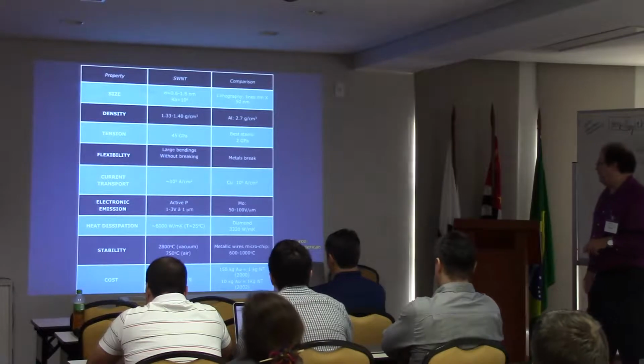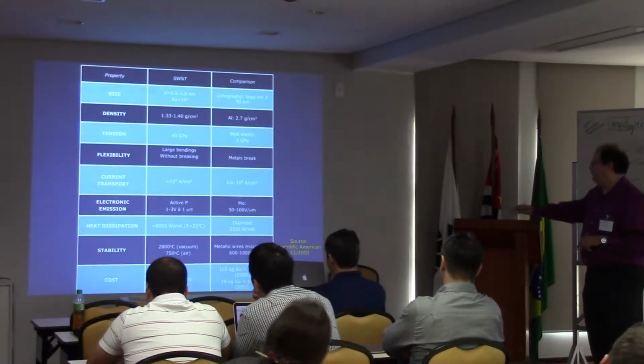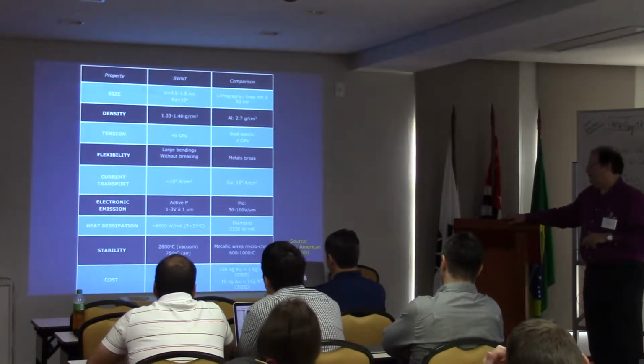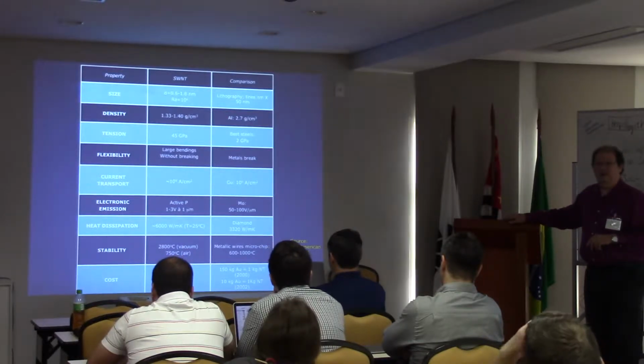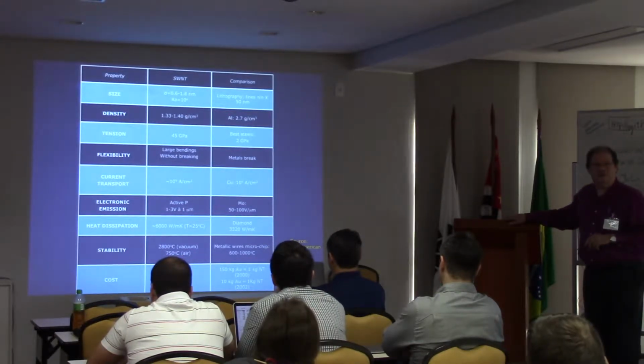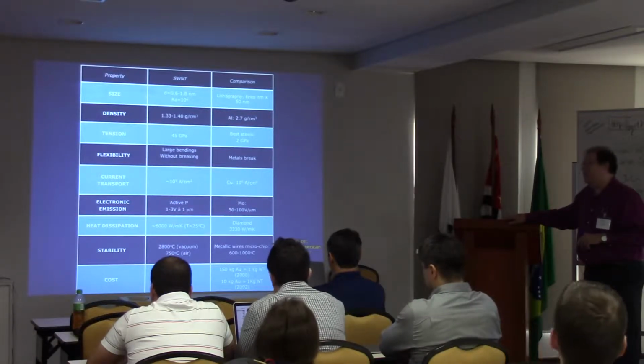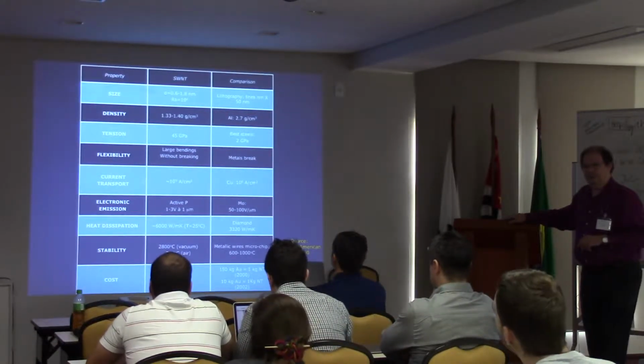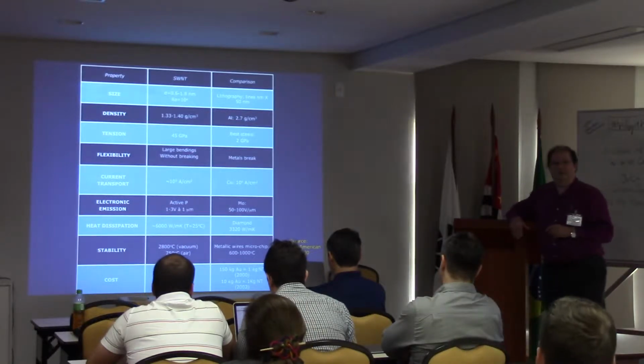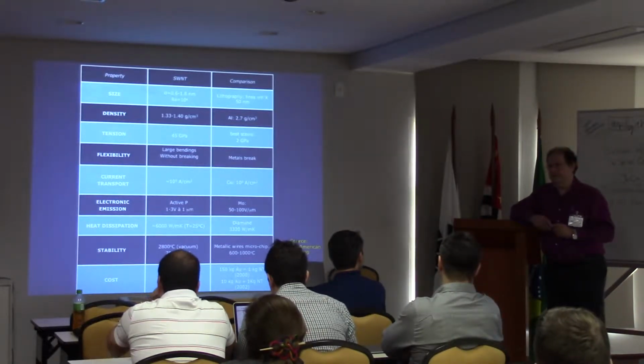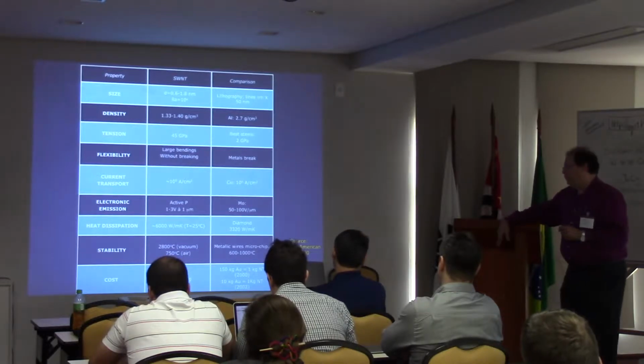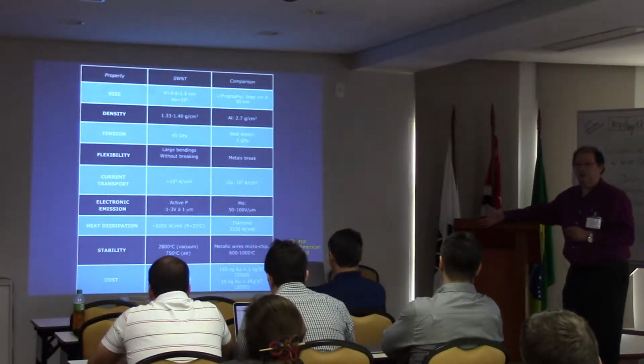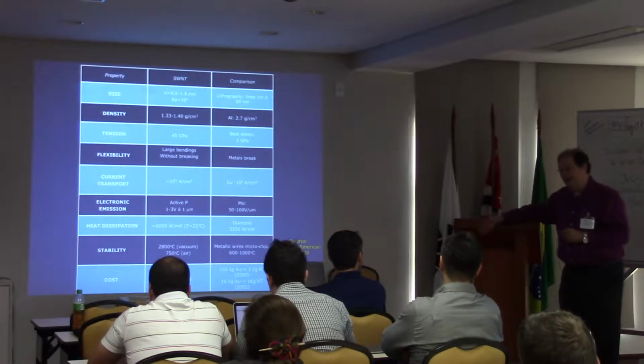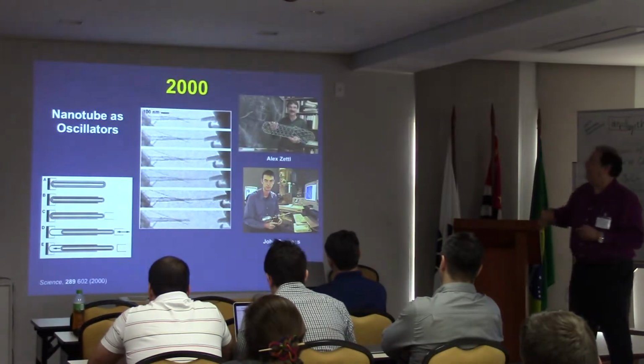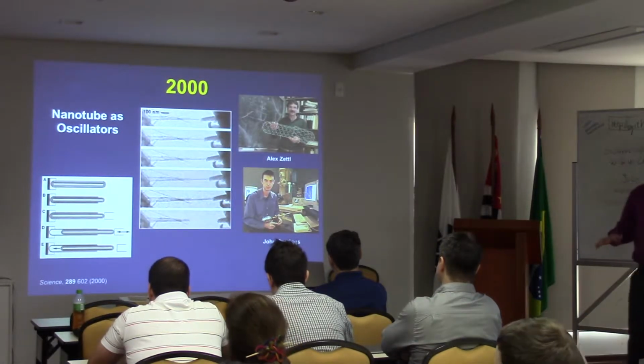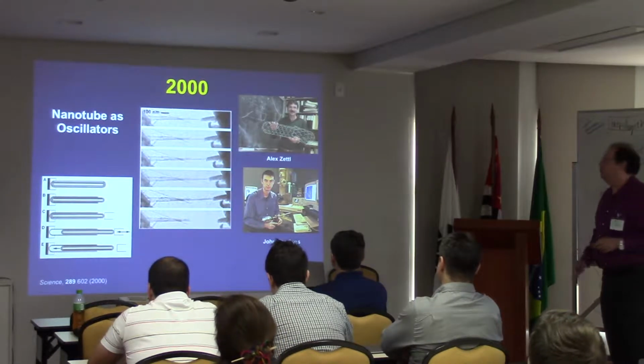These are data from 2000, and at that time you would need 150 kilograms of gold to have 1 kilogram of nanotubes. Nowadays these numbers are better, but it is still very expensive to buy high quality nanotubes, especially single-walled ones. Also, there is the problem I mentioned that you cannot control the chirality, the size, and the diameters. But for 10 years, people played with the electronic properties. Nobody paid attention to the mechanical properties.